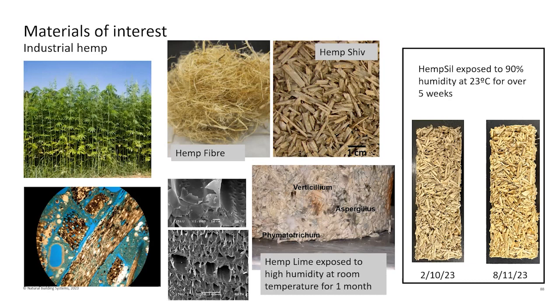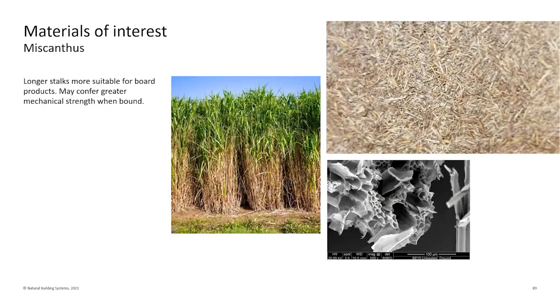One of the interesting things is a recent experiment I've been doing with the hemp sil. I stuck this into an environment chamber at 90% humidity at 23 degrees. The standard test for biodegradation is, will it last 28 days without mold growth? If you have no mold growth, you get a 0. If you have the whole thing covered in mold, you get a 5. And interestingly enough, we've gone 5 weeks and I haven't spotted any mold growth. So we are very resilient as a material, which is a very encouraging thing.